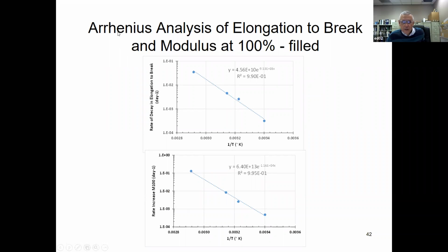Okay, so for the mechanism study, we use the Arrhenius technique, right? So here we have the rate of decay in elongation to break, and this is the rate of increase in the modulus at 100%. Going from 21 degrees to 70 degrees, we see no evidence for a change in the mechanism. And if we look at the modulus, going from 21 degrees C to 70 degrees C, no evidence for change in the mechanism of aging.